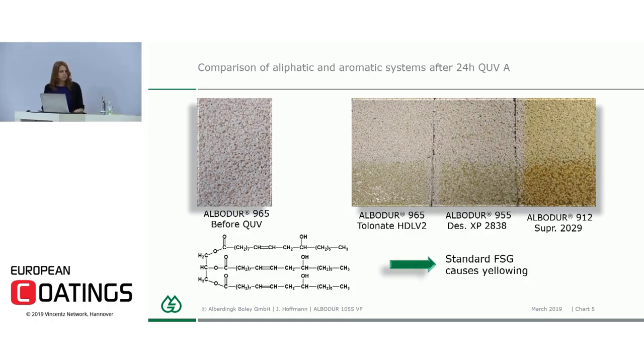So where is this UV yellowing coming from? As you can see, we still have some double bonds in castor oils. They cause the yellowing. But additional to that, castor oil is a renewable resource based on a natural oil. So that means we have a lot of side effects over the acid, which is still in the refined oil, and over the colorants, which are coming from the shell of the bean into the system. And that is also the reason why they are normally limited in saponification stability. 1055, because it is a super cleaned castor oil used for the production of the polyol, doesn't have that side effect. So it's much more saponification stable as well as UV stable.